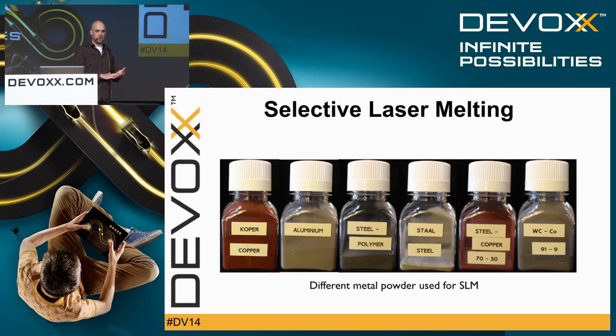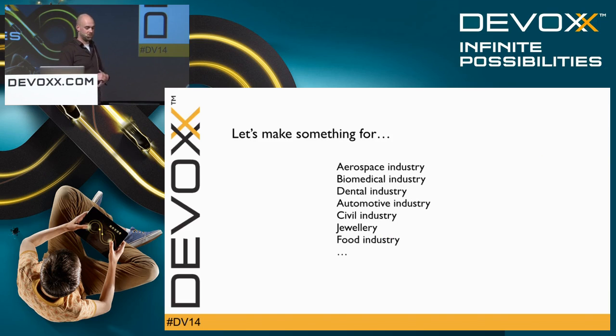Some of the materials are quite doable to print, but there are some other metals that are quite hard to manufacture, like copper for instance. Copper has a very high thermal conductivity, which means if you inject heat, the heat will dissipate away, and it's very hard to process materials like copper. That's still research today. Now let's see which industries are asking for 3D printed objects. And that actually starts from the aerospace until the food industry.